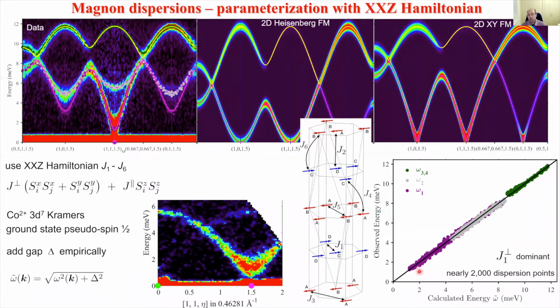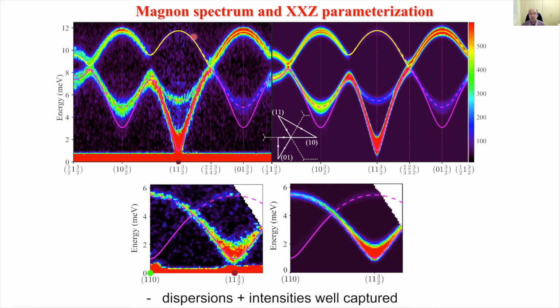we can obtain a very good parameterization of all the modulations that we've seen in many places in the Brillouin zone. So this is a one-to-one correspondence between the observed energy and calculated energy over thousands of dispersion points with very good agreement. And you can also see here that the calculated dispersions go through the dispersion points. So not only the dispersions, but also the intensity distribution is well captured by this parameterization, in a sense that the strongest mode is indeed observed as predicted, and also the intensity sharing between the modes, which modes are strong, which are weak, and so on, is well captured.